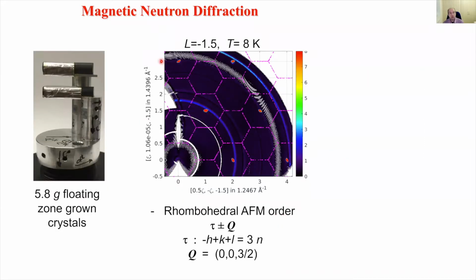So here's a picture of our sample mount for inelastic neutron experiments. Here we need a large sample mass, so we use 2 co-aligned single crystals to be able to have enough scattering centers to obtain a good signal. So here's a picture of the elastic scattering. So this gives us the information about the ordering, and these red spots are associated with a particular type of antiferromagnetic order.